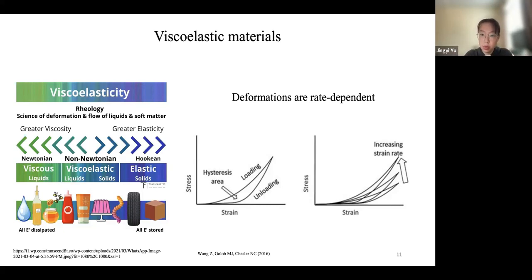One way we can test a viscoelastic material is by stretching the material at different strain rates. If we stretch them to the same stress, the slower we stretch it, the more time we allow it to deform, and it will reach a higher amount of deformation during that time. So with this, we're curious to see how the cell wall would behave. Would it stretch like a viscoelastic material?